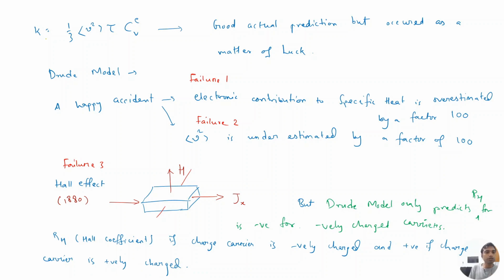So when we carefully look at the value of kappa, the thermal conductivity, this was matching very nicely with the experiment. But if you look at it very carefully, this is the result of a very happy accident. There are two terms here, you see the V square term, and there is this electronic specific heat term. These two are actually wrong in the framework of the Drude-Lorentz model.